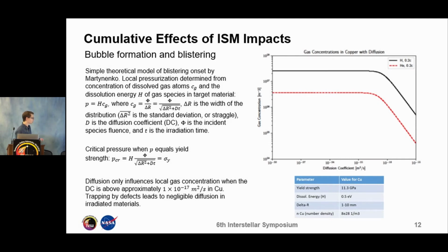However, you reach a critical concentration or a critical pressure when your pressure in the bubbles reaches the yield strength of your material. At that point, it leads to bubbles bursting because the material will fail.